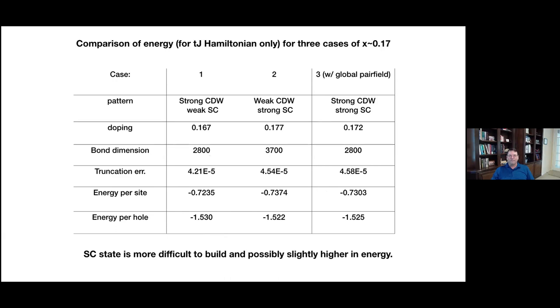So we seem to have a clear case. First of all, we're seeing some states, these stronger superconducting states, that we didn't see in the early days of the t-J model with these vertical stripes. The vertical stripes tend to gap out superconductivity if the stripes are too strong. How does superconductivity work? Superconductivity works from pairs delocalizing into a Bose condensed gas. For that to happen, the pairs have to come on and off the stripes pretty freely. If they're just stuck on the stripes because of an energy difference between different numbers of holes in the stripe, you won't get much. That seemed to be what we usually saw in the earlier days with the vertical stripes. We didn't get much of a response, but in this case, there are some states very close by, a little bit harder to access with DMRG, that are showing the stronger stripe pairing.